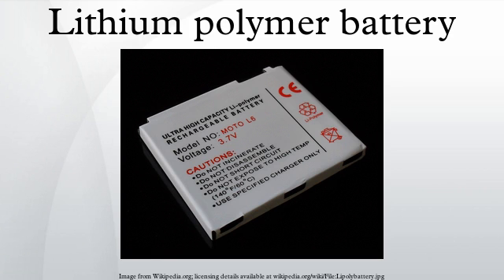A compelling advantage of LiPo cells is that manufacturers can shape the battery in different shapes, which can be important in applications requiring a small footprint for the energy storage system, like thinner and lighter mobile phones and notebook computers. LiPo batteries are gaining favor in the world of radio-controlled aircraft, radio-controlled cars and large-scale model trains, where the advantages of lower weight and increased capacity and power delivery justify the price. As of the beginning of 2013, LiPo packs of 1.3 Ah exist providing 45C continuous discharge and short-time 90C bursts. Bigger packs of 4.5 Ah may feature discharge rates of 70C with 140C bursts. LiPo packs also see widespread use in airsoft, where their higher discharge currents and better energy density compared to more traditional NiMH batteries provide a very noticeable performance gain.